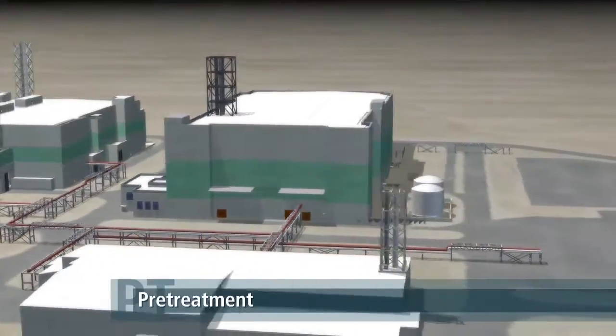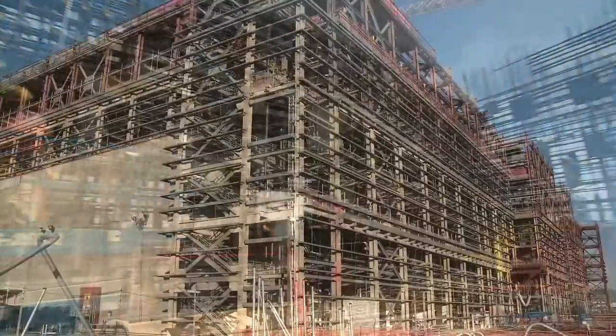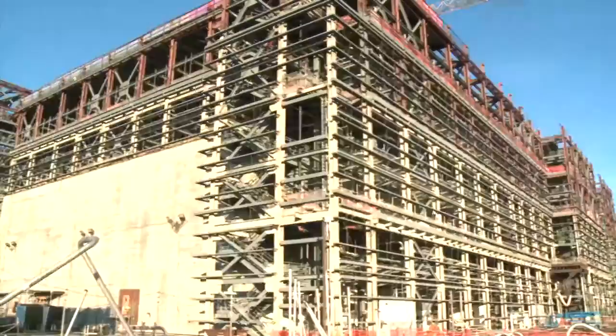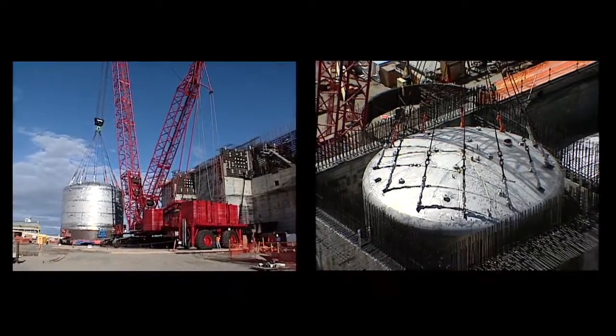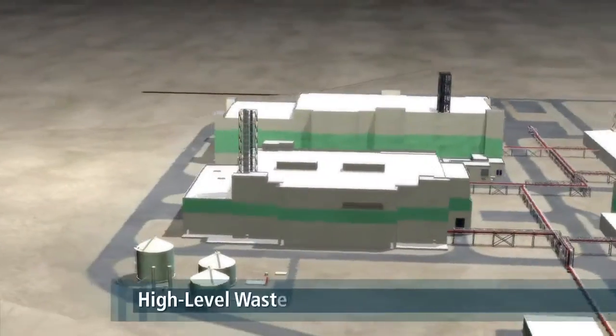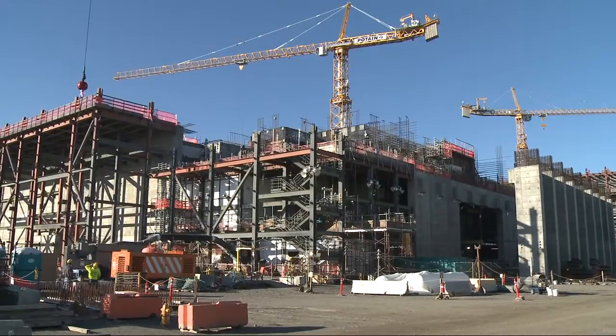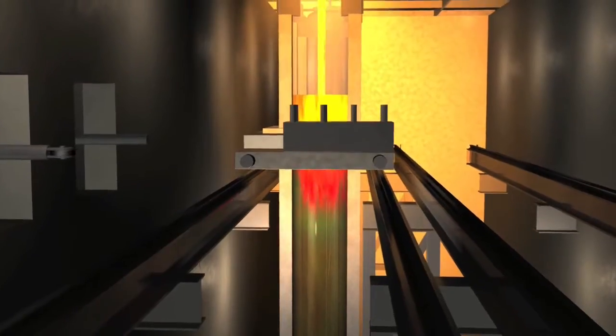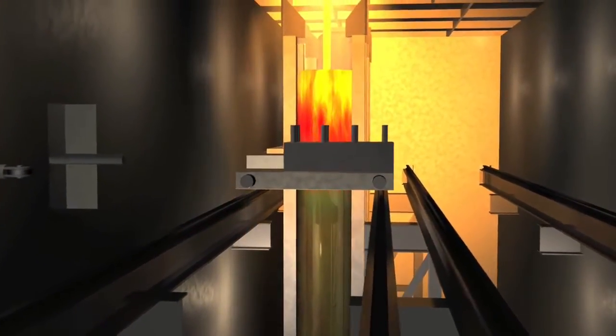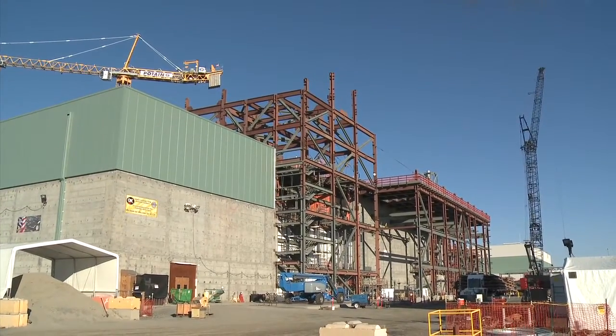The pre-treatment facility will be the world's largest and most technologically complex nuclear chemical separations facility. The building is nearing its total height of 120 feet tall, and huge stainless steel vessels are in place to receive and process the waste. The high-level waste vitrification facility will house two 90-ton melters to turn radioactive waste into glass. The molten glass will be poured into 14-foot tall stainless steel canisters, and the facility will produce 6 tons of glass per day — about 480 canisters per year.